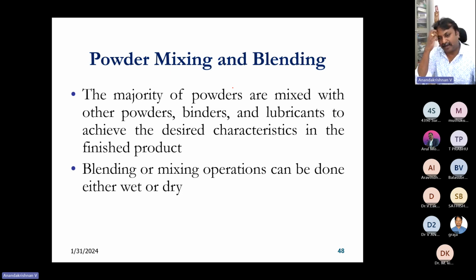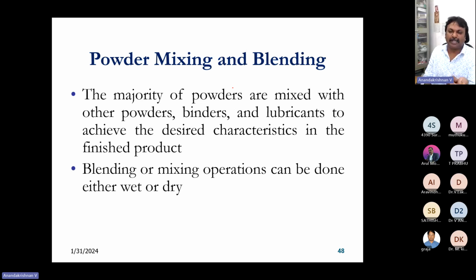Then mixing of this powder is again important. As I told you, the powder metallurgy technique is a very good technique where you can add any kind of powders. For example, if you are going to create an alloy, there are limitations. You have to go for a binary phase diagram or a ternary phase diagram. But here in powder blending, you can take 50% of copper, 50% of aluminium, or 10% of titanium carbide. You mix it together and create a consolidated shape by consolidating all this powder, and you can heat it at the lowest temperature at which it can sinter, and you can create some components.